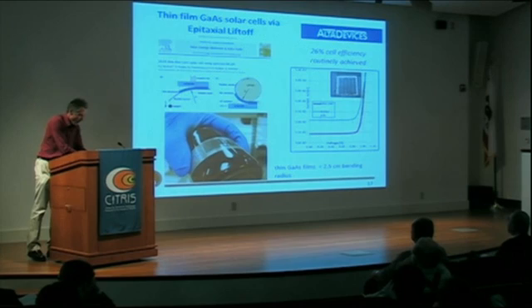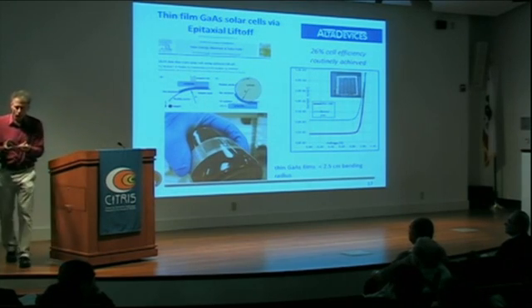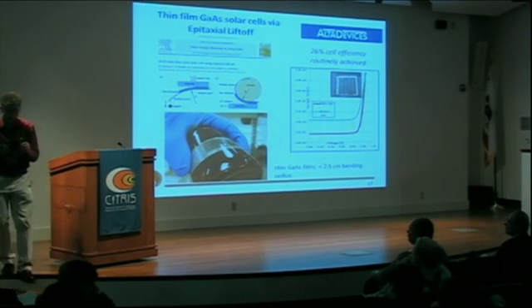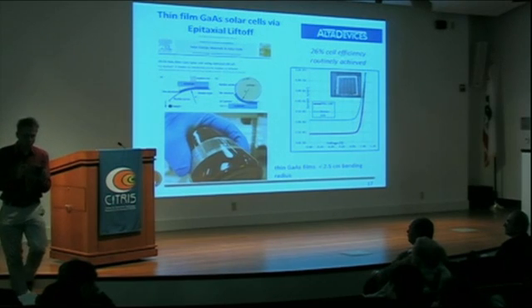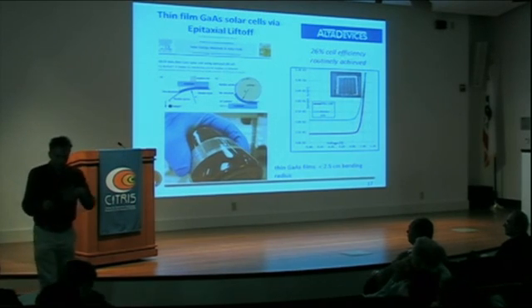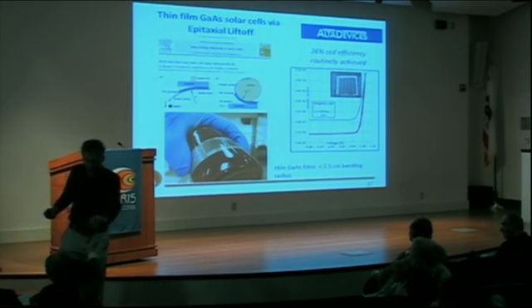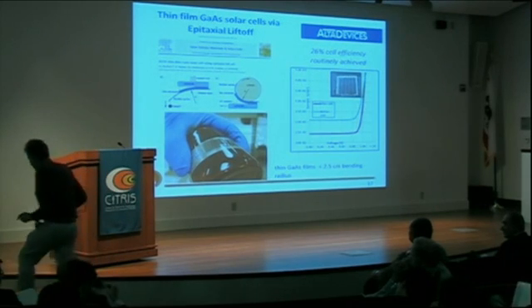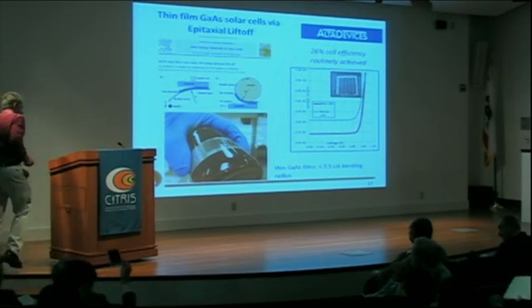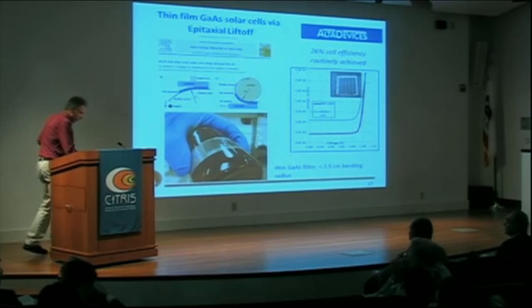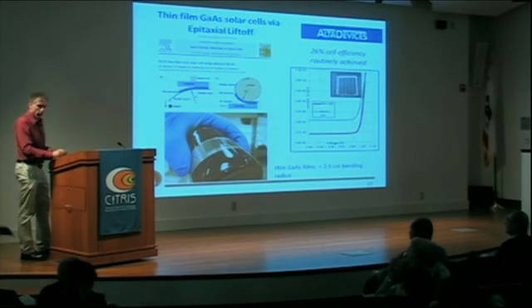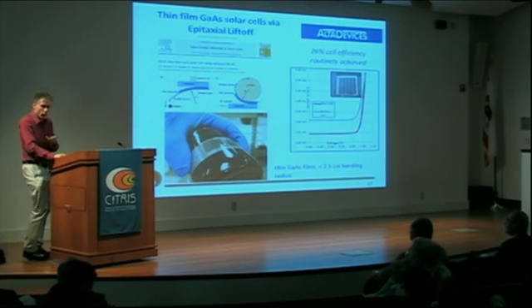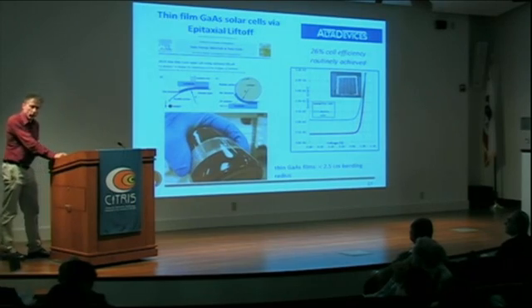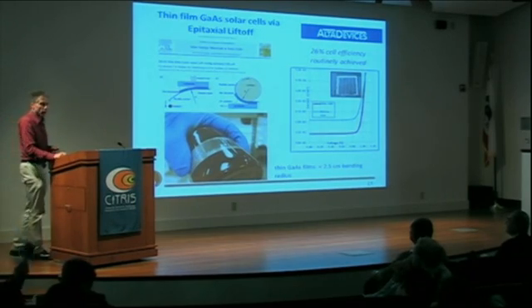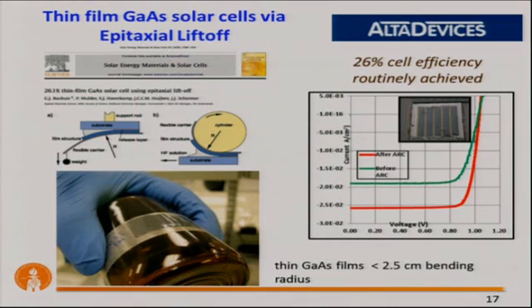And here I'll pass around these cells that when they're peeled off the rigid substrate, they can be put on, they're extremely flexible with a metallic backing. These are cells made for gallium arsenide. These are single crystals of gallium arsenide. I think that's an unprecedented size, at least in conventional thinking, for a solar cell. And these cells have routinely efficiencies in the 25 to 26% range.